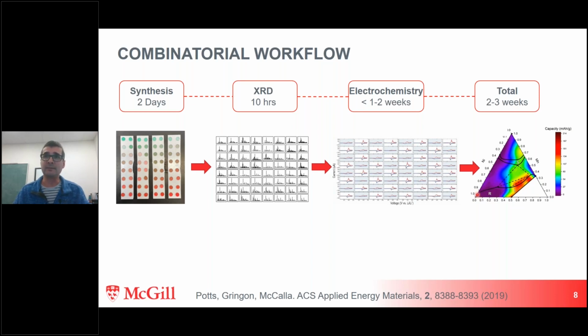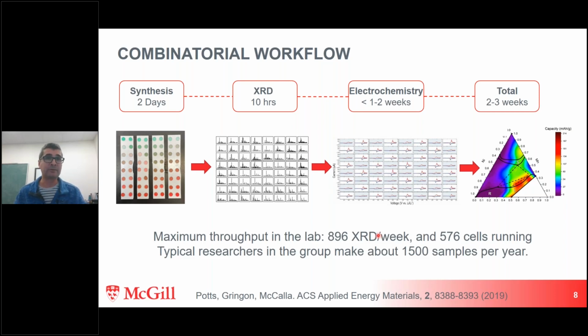And so we have the structure in this phase diagram. We can see these boundaries of these single phase regions. And then we also have the electrochemical performance in the color. So we can map the battery performance to the composition and the structure very efficiently. So the maximum throughput of the lab is almost 900 XRDs a week. It takes 2 minutes to load them, and then they run for 10 hours. So we do that twice a day, and that's 45,000 XRDs a year is the maximum throughput of the lab. We can have almost 600 cells running at once. Actually, this is old. 640 is what we can do now.